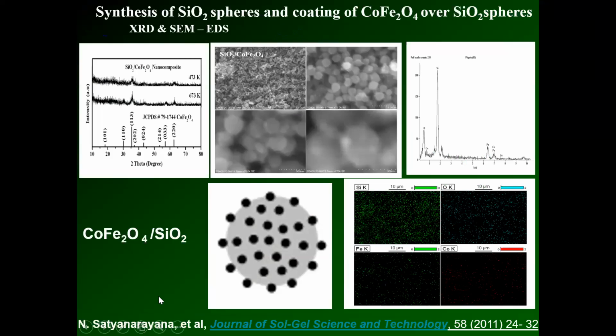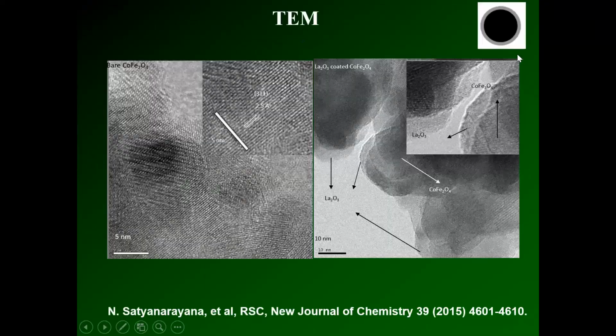The next one is you can do a core shell type. You can see that lanthanum oxide is coated over the cobalt ferrite. This way you can get this, and like this you can do vice versa also, depending upon your requirement. Here they want to have a cathode material coated with lanthanum, and they confirmed it using the SAD pattern of the TEM. You can see the values exactly match.